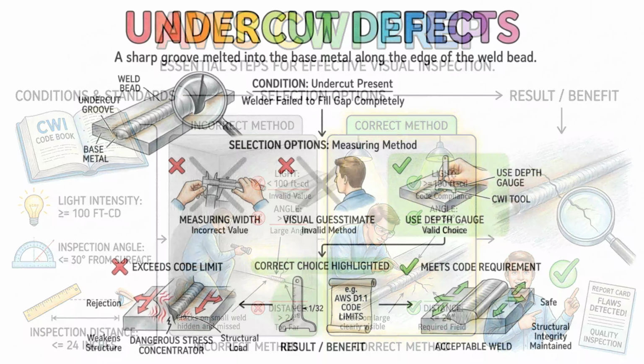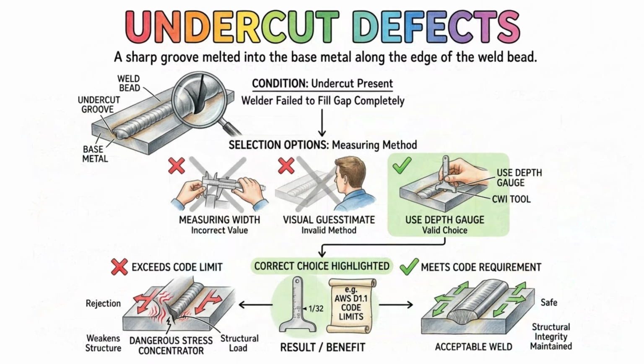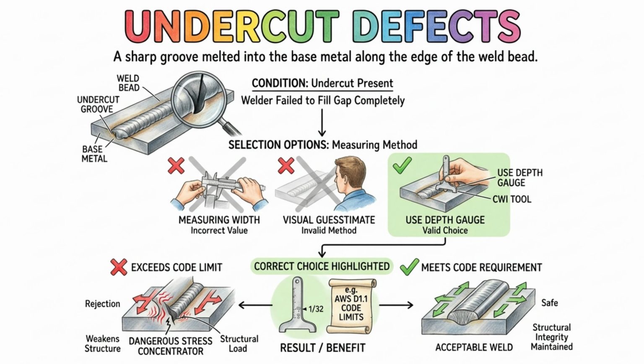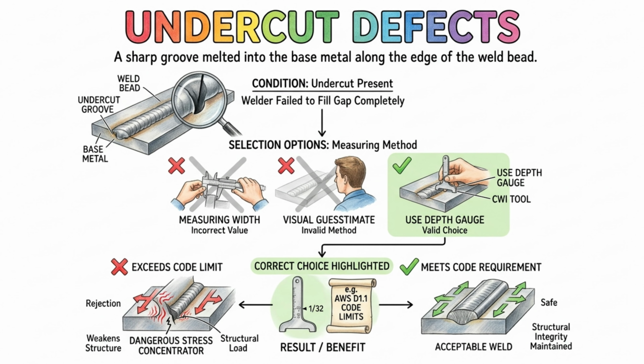One of the most common surface flaws you will encounter on the exam and in the field is undercut. Undercut is a sharp groove melted into the base metal right along the edge of the weld bead, where the welder failed to fill the gap completely. This defect is dangerous because it acts as a stress concentrator, meaning it concentrates all the structural load onto a tiny, thin line of metal. You must use a depth gauge to measure how deep the undercut goes, because welding codes strictly limit how much undercut is legally allowed.